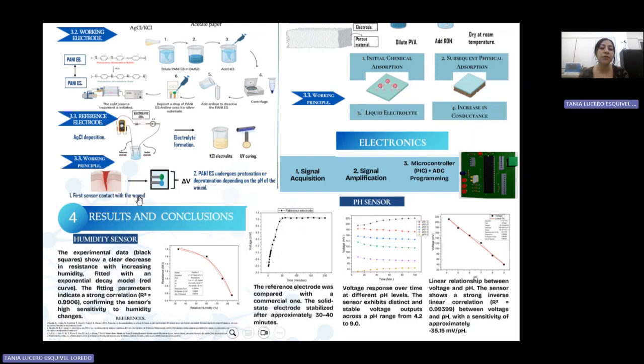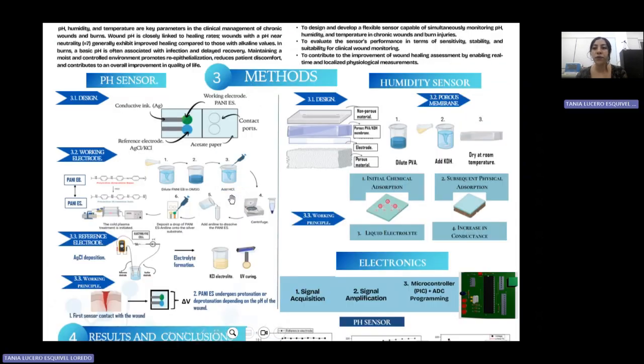So the working principle for this sensor is that when the sensor makes contact with the wound environment, the PANI layer undergoes protonation or deprotonation depending on the pH. If it's acid, then it's protonation. If it's alkaline, then it's deprotonation. And this results in a measurable potential difference between the electrodes, and that's what we can sense through electronics.